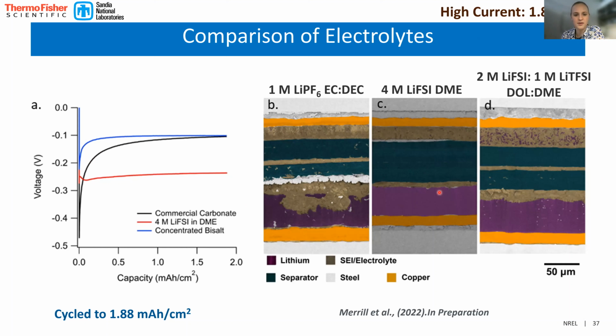The 4 molar lithium FSI and DME was more stable, but very small lithium deposits, and again, not a very good network for this, but less of that pitting behavior was observed in the concentrated bisalt electrolyte.